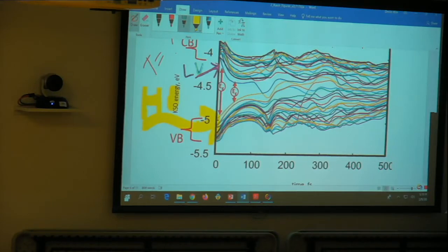For the DOS figure, you were taking temperature as 0. But in real life, it's not possible to achieve 0 Kelvin. So in real life, the orbital energies will start to fluctuate and the gap shrinks. Sometimes it shrinks even to 0.